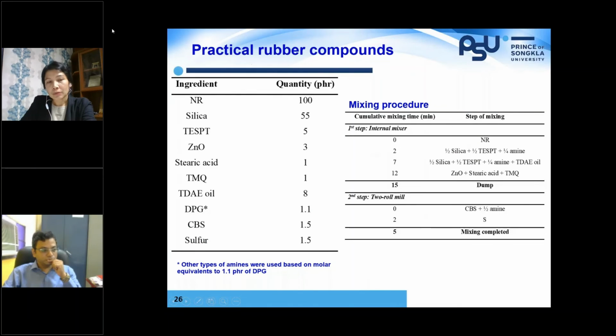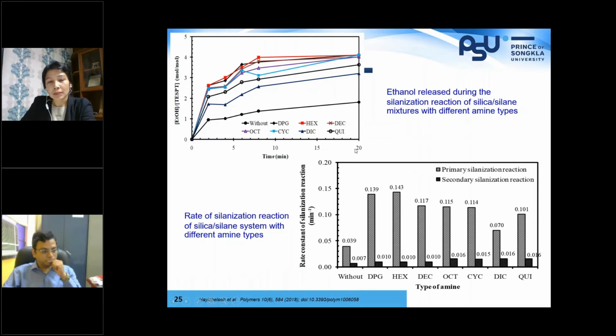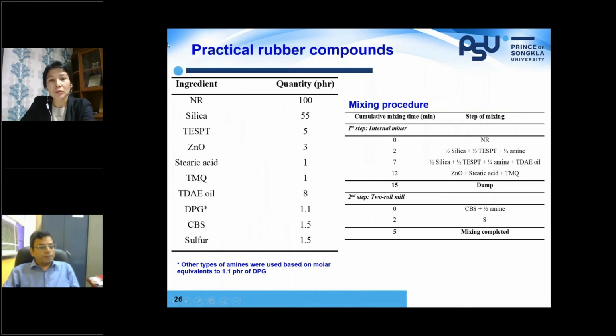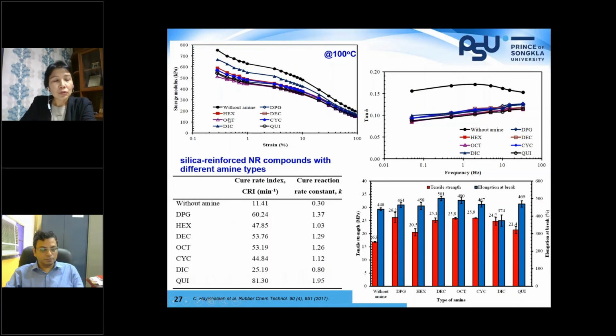When we look at the compound, because we can see nice chemistry in the model study, but we want to see whether it works in the real or practical compound. So we use those different amine types based on molar equivalent, using this formulation following two mixing steps as I show here. I show you here a plot of storage modulus versus strain. This is a kind of Payne effect study.